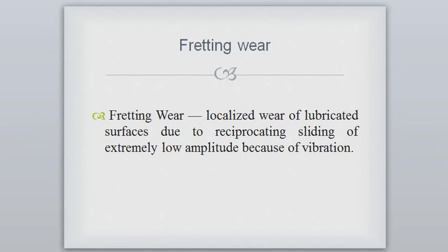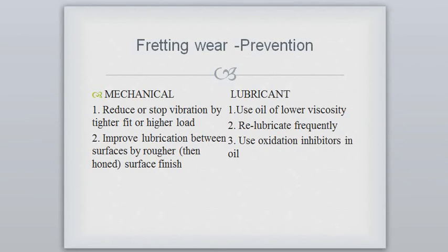Next is fretting wear. Fretting wear is a localized wear of lubricated surfaces due to reciprocating sliding of extreme low amplitude caused by vibration. Preventions: mechanically, reduce or stop vibration by tighter fit and higher load, and improve lubrication between surfaces by rougher surface finish. For lubricant, use oil of lower viscosity, re-lubricate frequently, and use oxidation inhibitors in the oil.